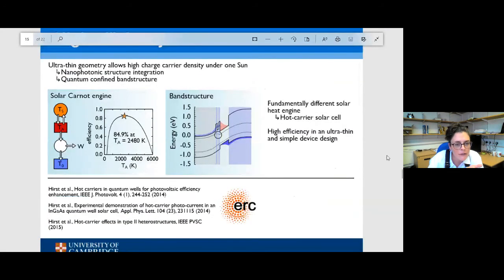So on the more fundamental side of things, one of the things that we're interested in is moving towards high efficiency. I mentioned that briefly as one of the key targets for space photovoltaics. Something that happens with ultra-thin geometries quite inherently, when we include some kind of light management structure, is that we're absorbing more photons in a thinner volume of material. So we end up with a higher charge carrier density for a given level of illumination. What that does is we will inherently see a local increase in our quasi-Fermi level splitting, and ultimately that can manifest as a higher voltage device. So with an ultra-thin geometry, you absolutely can break the single junction Shockley-Queisser limit because you break down some of the assumptions that actually go into calculating that limit.